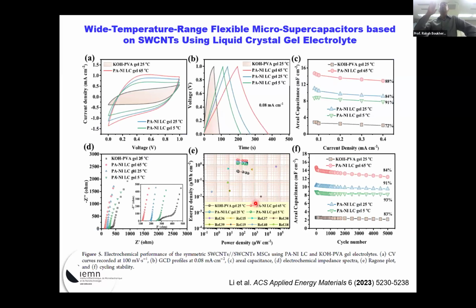When you record, we used two different gel electrolytes, PVA potassium hydroxide, but also this liquid crystalline-based gel. What you can see is that we can operate at different temperatures, and it also gives much higher energy efficiency when you use this liquid crystal. And this liquid crystal is really easy to make. It's not very difficult, it's very simple. So you can achieve really high energy storage performance.